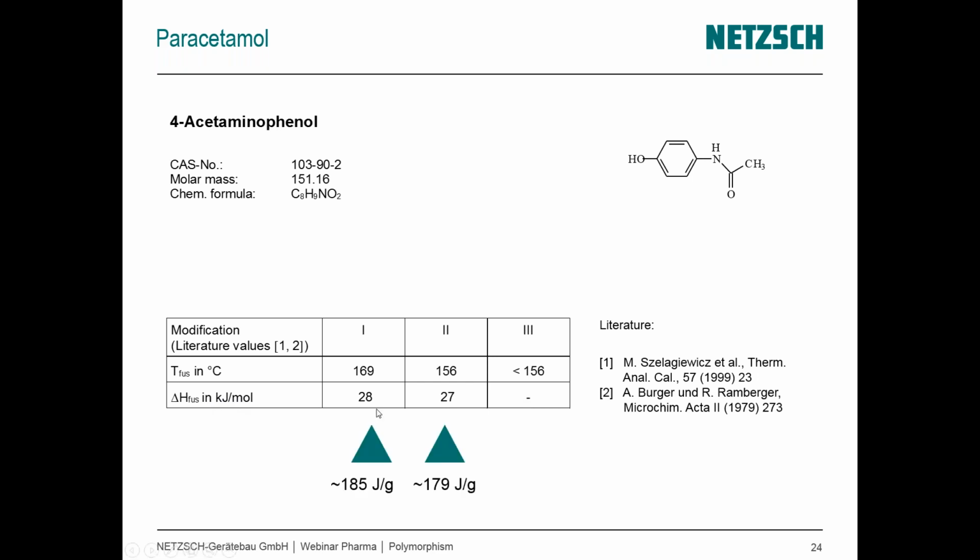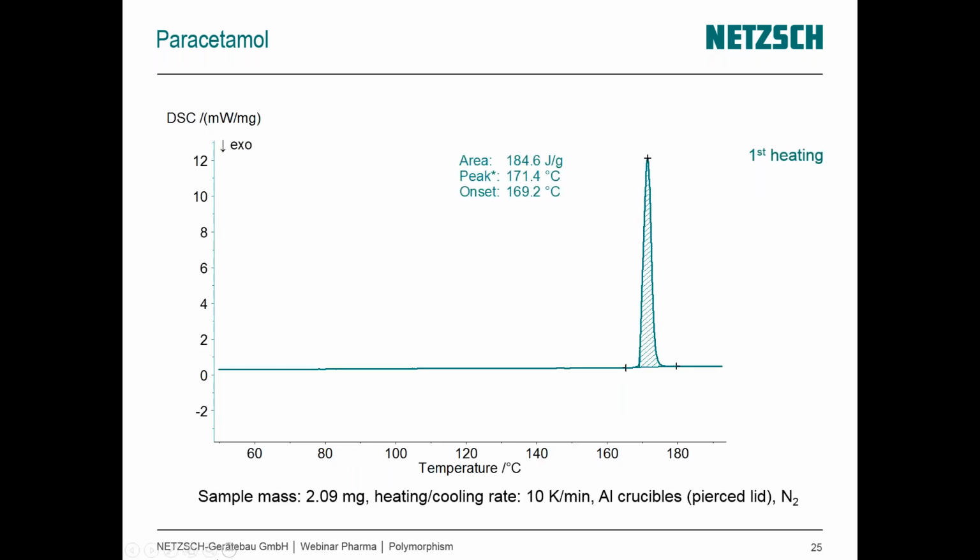In some of these situations, we don't have a set heat of fusion that can be found. If we look up literature values, often what we'll see is kilojoules per mole. What we do then, if we want to look at this in terms of the DSC and the way that we've prepped our sample, is we can see the amount of joules per gram, so the area under the curve of melting for these two different forms.